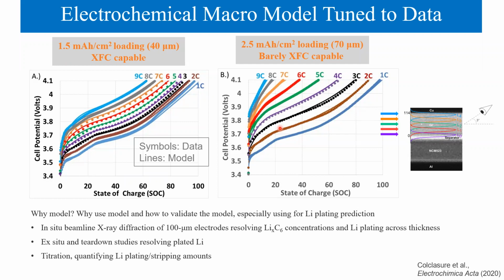provide guidance on cell designs and requirements to improve fast charging acceptance at 4C to 6C CC charging, and electrolyte depleting for cells incorporating loading beyond 3 milliampere hour per centimeter square. The electrochemical model has been validated for low loading and moderate loading cells. Based on all experimental data, prediction of fast charging limitations such as electrolyte depletion and onset of lithium plating are reasonable. Model also compared with the recent 1C rate operando XRD measurement from Argonne National Lab.